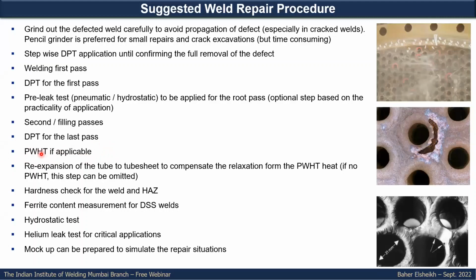Application of the post-welding treatment inside the tube sheet is not an easy application to confirm the uniform and proper heat distribution. It shall be carefully applied, and in some cases you might need to do finite element analysis to confirm that thermal and mechanical stresses during the application are within the accepted values, which will not harm the equipment.